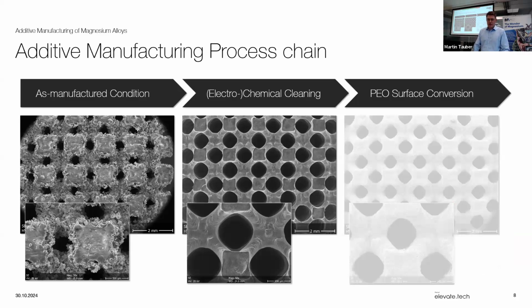So as you see on the left-hand side, the material, once we get it from the additive manufacturing process, is quite rough on the surface. We have many sintered powder particles on the surface, and the final shape that we want isn't met already. So what we have to do is electrochemical cleaning, which is a process that we also developed in-house. And the shape that we're looking at now is a 3D complex porous structure.